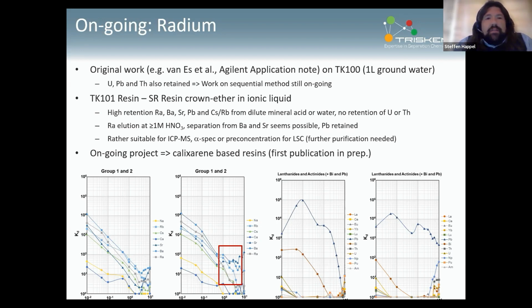It's getting a bit better. That's uranium, thorium are not retained on these. There's still quite wide range of elements that are retained. Radium, barium, strontium, lead, mostly cesium, which might be a little less problematic in normal environment samples. Then radium elution at 1 molar nitric acid. As you can see, chemistry is getting a bit messy here, and that's something that we're at the moment trying to figure out, getting a bit more precise data.